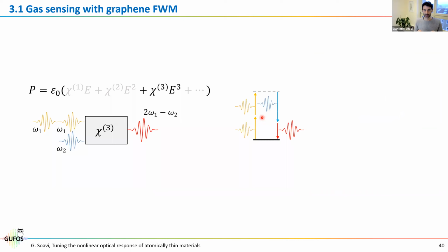The first one is related to gas sensing using graphene four-wave mixing. So what we do is again the following: we take a graphene, and then I will show you in a second the device. But we have again graphene, a centrosymmetric material, so we look at the chi3. And the process we look at now is a 4-wave mixing, so not a third harmonic generation. 4-wave mixing is a process where we have 2 photons in at h bar omega 1, another photon in at h bar omega 2, and at the output, we take the difference 2 omega 1 minus omega 2. So you can see the energy conservation here. You have 2 photons omega 1, 1 photon omega 2, and we look at this difference here. So this 4-wave mixing at the output.